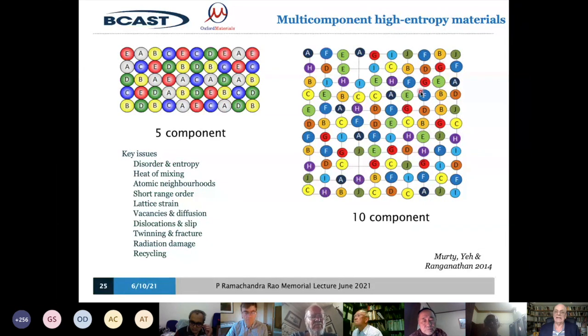But let's notice first that difference in local environments produces a slight straining in the material. What do I mean by a straining? Well, these atoms are all different sizes and slightly different electronic structure, so the lattice is not so perfect. If you have a small A atom here, then it gets squeezed in a bit. The others shrink in a little bit. If you get a large C atom, then it pushes the others out. So there are small strains in the lattice throughout associated with this wide variation in local environments.